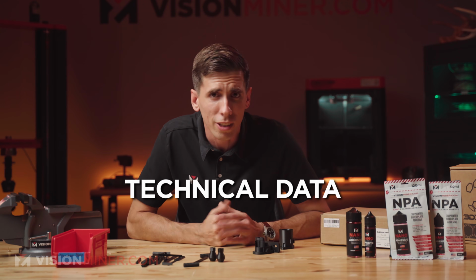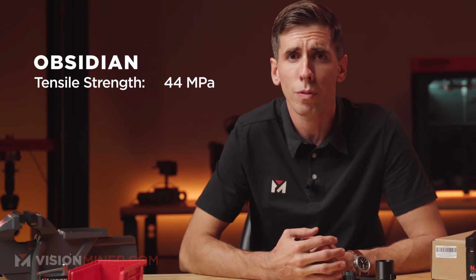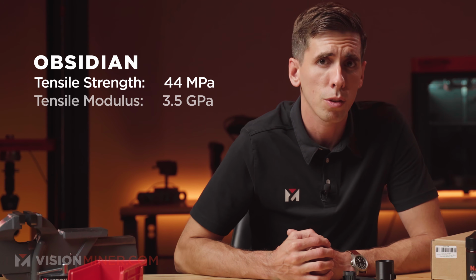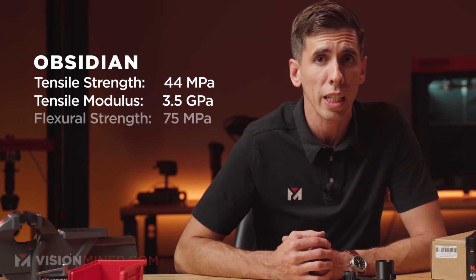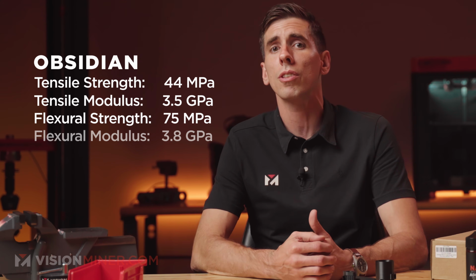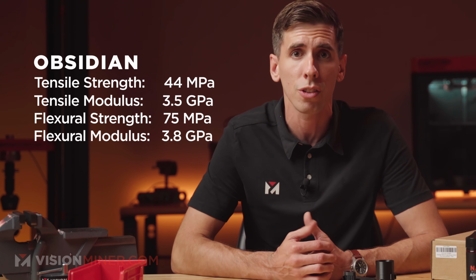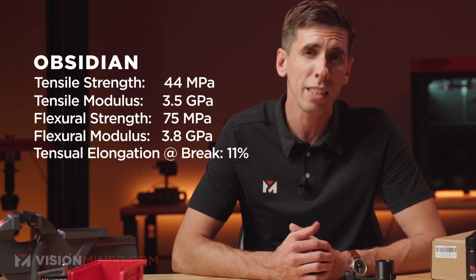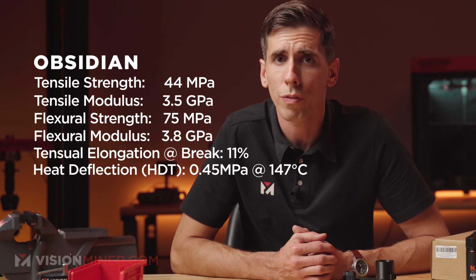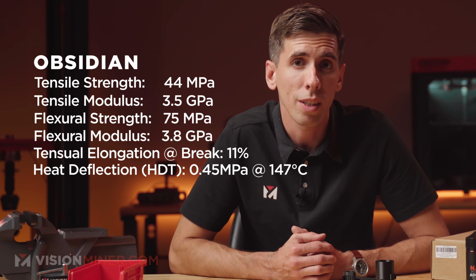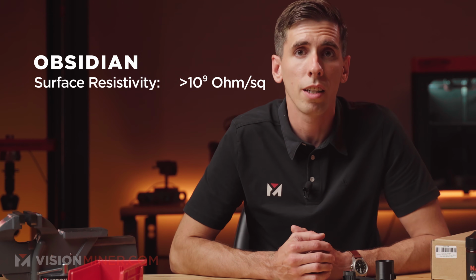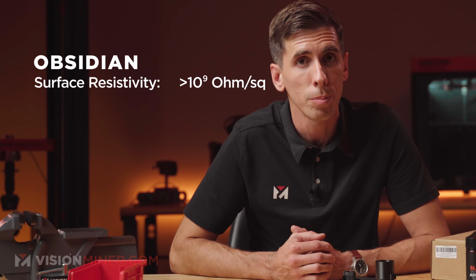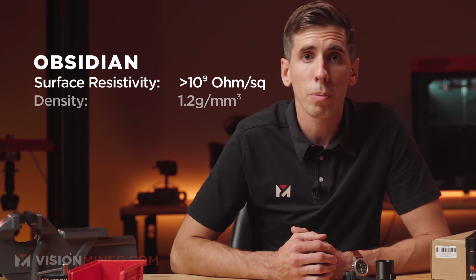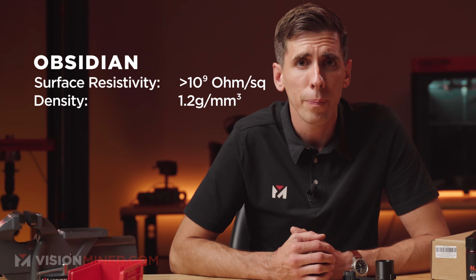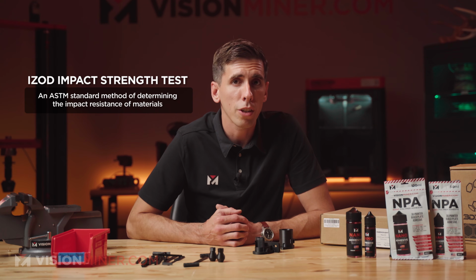Technical data, the TDS, let's hit the specs. Here's what you get, and here's what Obsidian brings to the table. You got a tensile strength of 44 megapascals. You get a tensile modulus of 3.5 gigapascals, a flexural strength of 75 megapascals, a flexural modulus of 3.8 gigapascals, a tensile elongation at break of 11%, a heat deflection temperature at 0.45 MPa of 147 Celsius, with a surface resistivity of greater than 10 to the 9th ohms, so it's very insulating, the density of 1.2 grams per cubic centimeter, and no published Izod impact, but